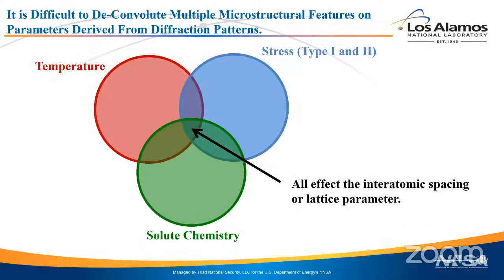Now, there's a problem with using diffraction to pull out microstructural features. I just showed you three different things you can essentially pull out of a diffraction pattern, and there are about 900 things in the microstructure that can affect those three things. How you deconvolute those effects is what takes you from, okay, interesting idea, to, okay, that really impacts material science. The simplest one is the spacing between the atoms, right? We use diffraction to measure the spacing between atoms very accurately, to about 10 parts per million. Think about that. That means we're measuring the spacing between atoms to femtometer accuracy. And it's actually not that hard to do. But how do you interpret that?